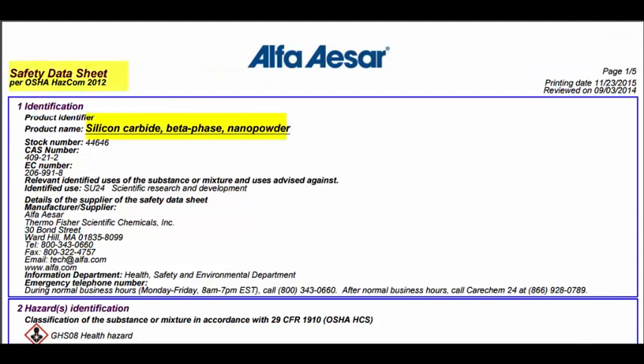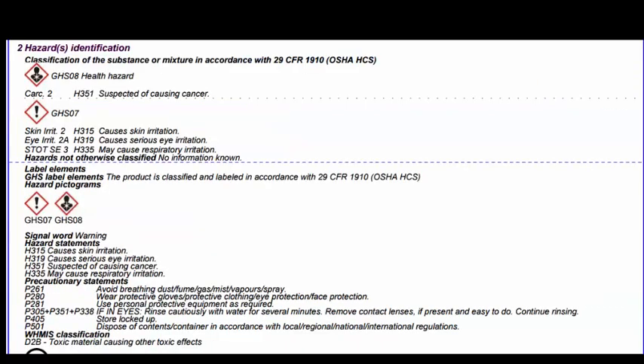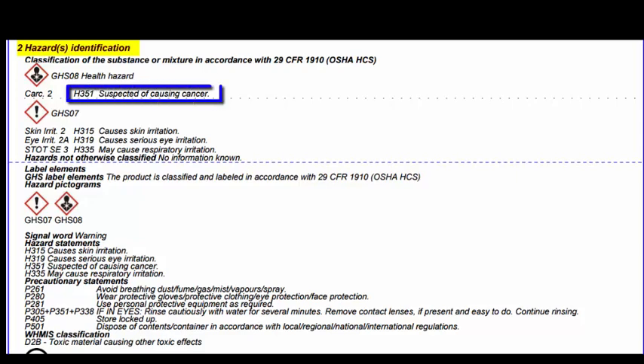Next, to determine the occupational exposure band of silicon carbide beta-phase nanopowder, go to the Hazard Identification section of the SDS. Locate the classification and H codes of silicon carbide on the SDS. Here, the codes are H351, which means it is a suspected carcinogen; H315, which means it causes skin irritation; H319, which means it causes serious eye irritation; and H335, implying it may cause respiratory irritation.